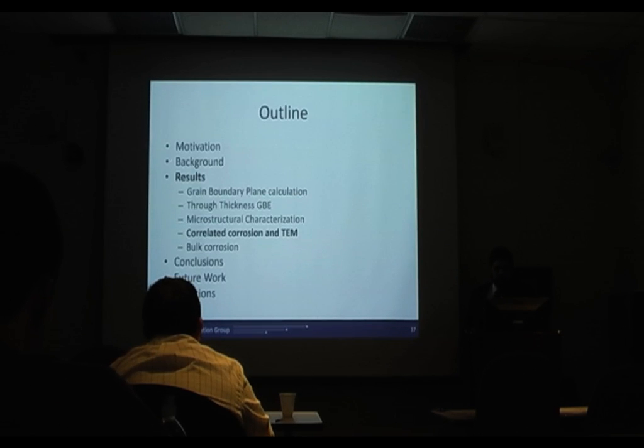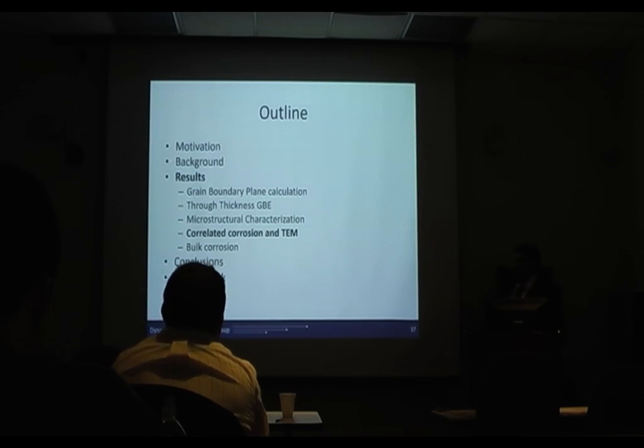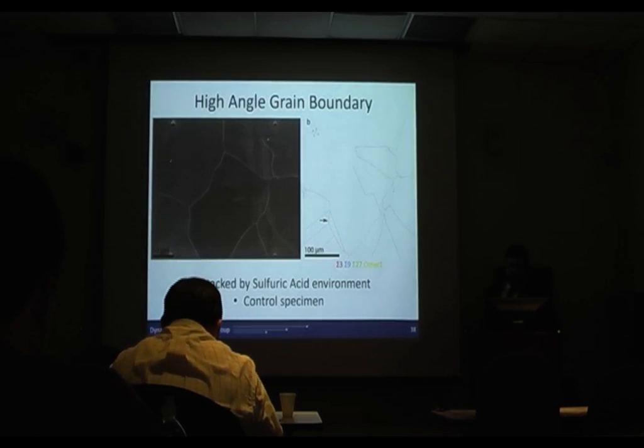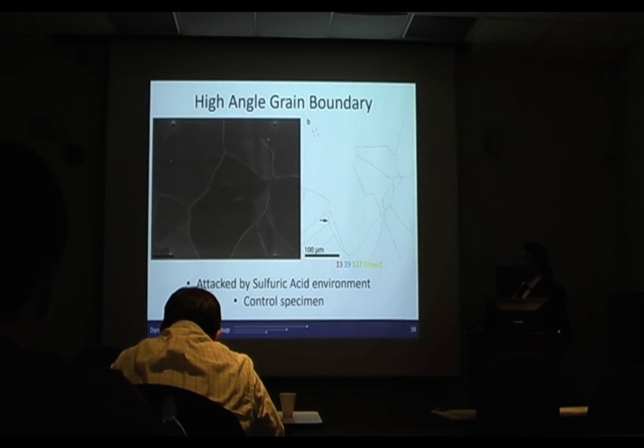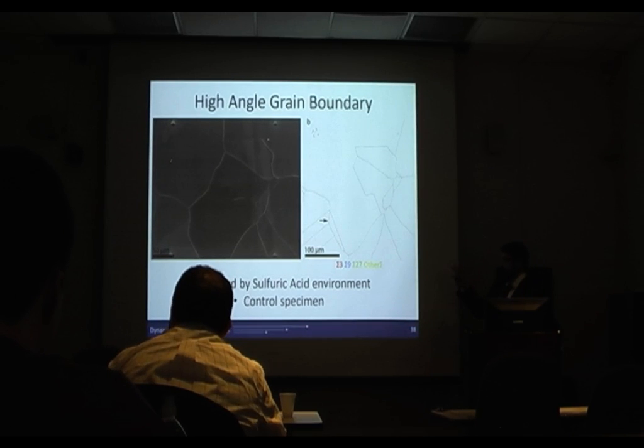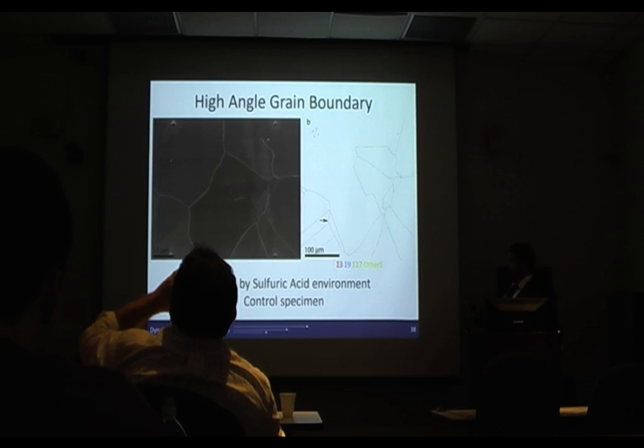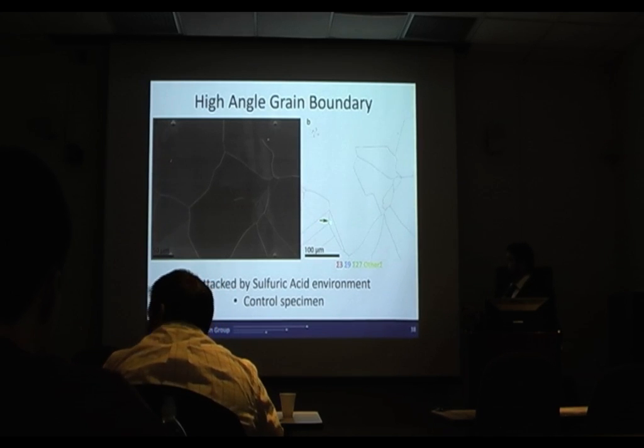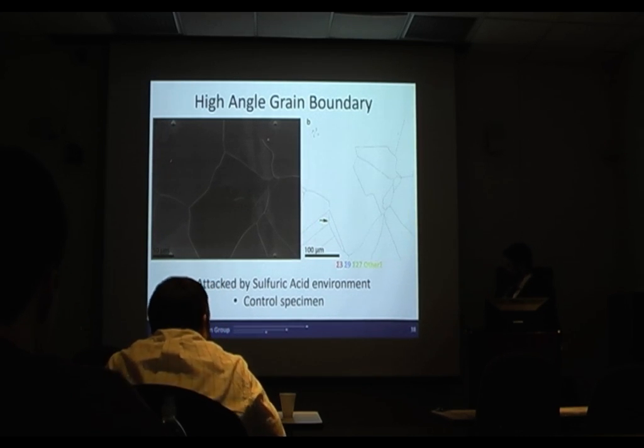So moving on to the correlated corrosion in TEM. Here on the left is the SEM image of a corroded microstructure. This is exposed for 4.5 hours in a sulfuric acid bath. And on the right is the EBSD map, and the arrow here shows where we made a FIB lift out. And this is just a random high angle grain boundary to serve as our control specimen.